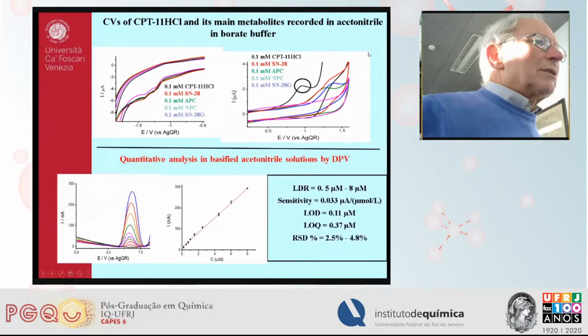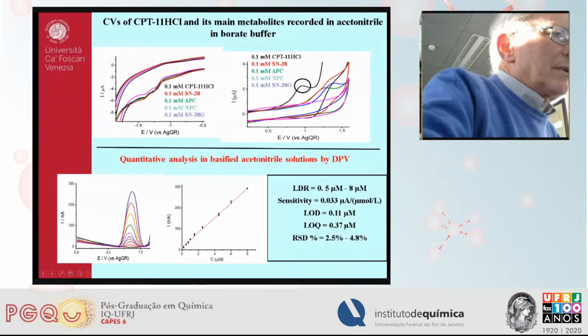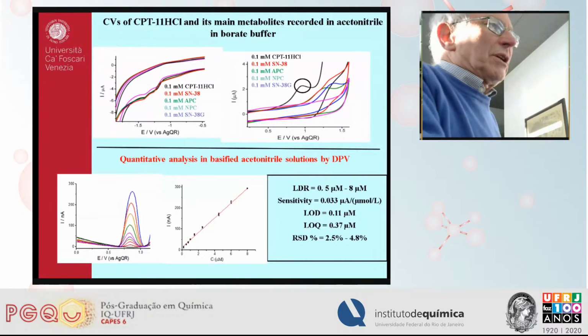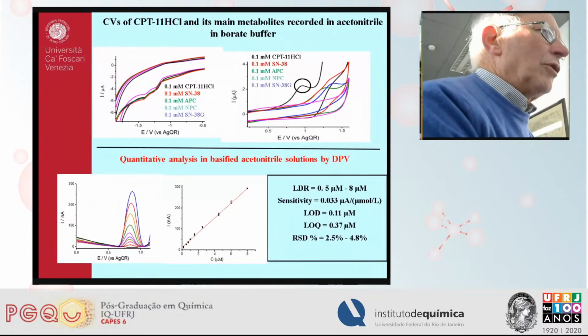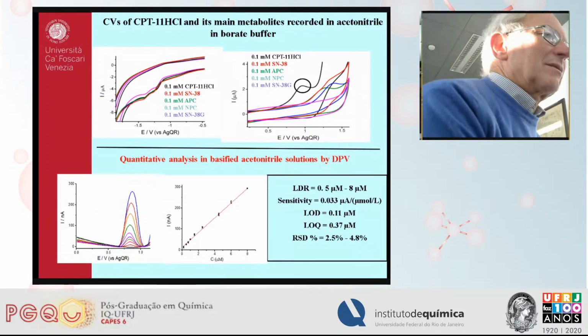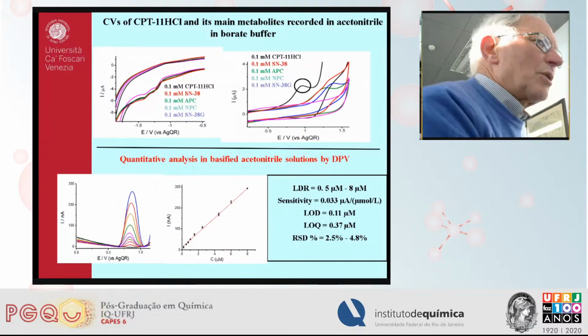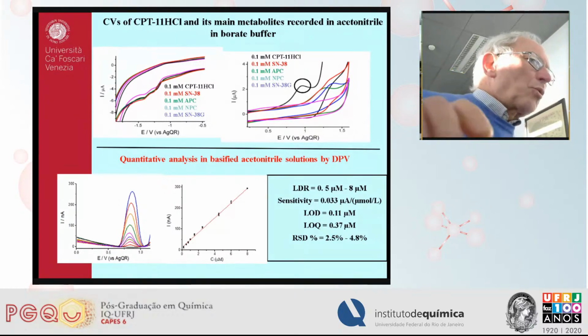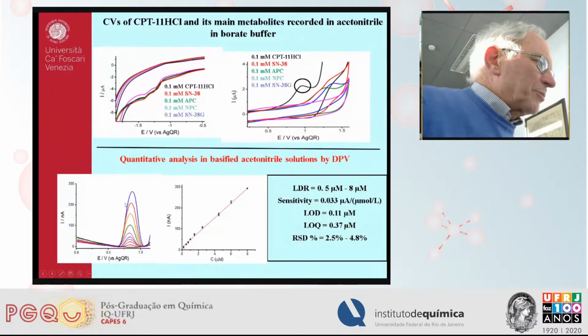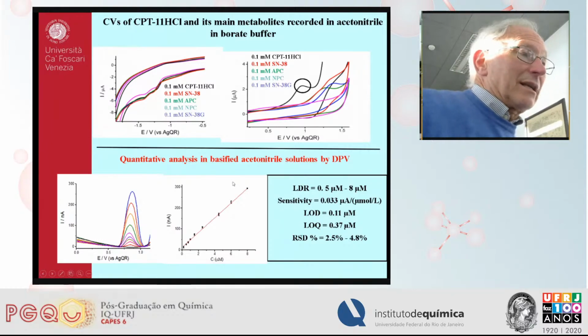Cyclic voltammetry is not typically a technique used for quantitative analysis because it's not very sensitive. So in order to quantify the compounds at trace levels, differential pulse voltammetry is preferred. So we used DPV, which provides responses like those shown here, which are bell-shaped, peak-shaped. And by using this technique, we could detect CPT11 at the simple glassy carbon electrode with this kind of analytical characteristics.